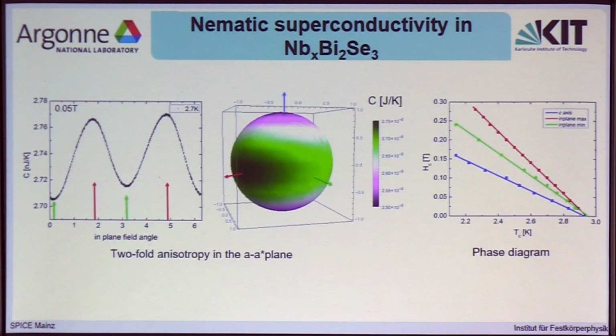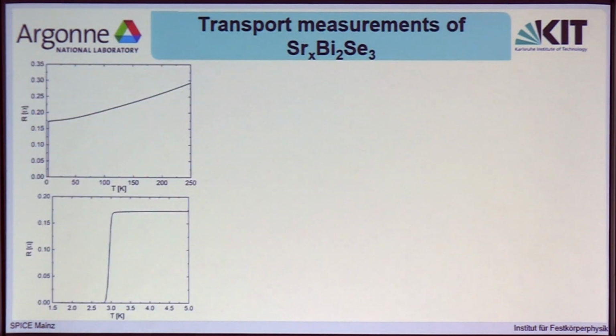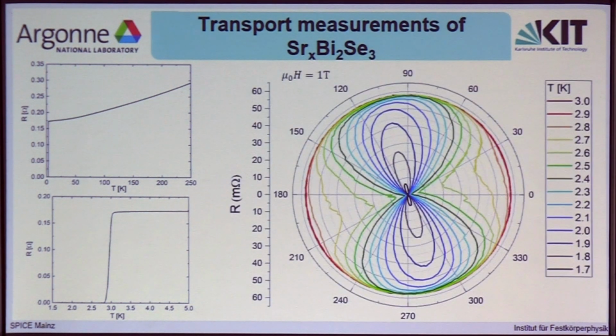Now a third proof for this twofold anisotropy comes from transport measurements. And here you see transport measurements for strontium-doped bismuth selenide, the cool down from room temperature, and then a zoom into the superconducting region. And also here, what is very nice for transport measurements, as they're very sensitive, you can apply a field of 1 Tesla in the plane. And then what you do, you stay at a constant temperature, you rotate the field, and you get these nice